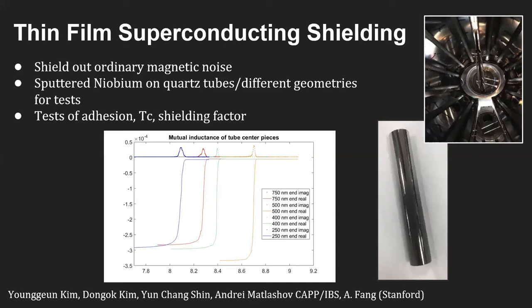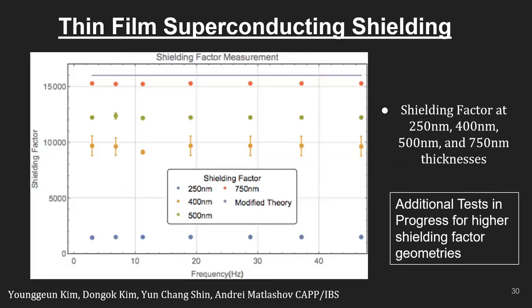In particular, we've done some tests of adhesion, the superconducting transition temperature, and also the magnetic shielding factor for different types of thin film niobium coatings. We've studied, for example, the shielding factor dependence on the thickness of the coating and shown how we can approach the theoretical value as the thickness of the coating gets thicker, closer to 1 micron, which is close to our target thickness. There are some additional tests currently in progress to study this under conditions of higher shielding factors that are closer to what we're aiming for in the experiment, where to get our full sensitivity, we'd ultimately like to demonstrate a shielding factor of around 10 to the 8.